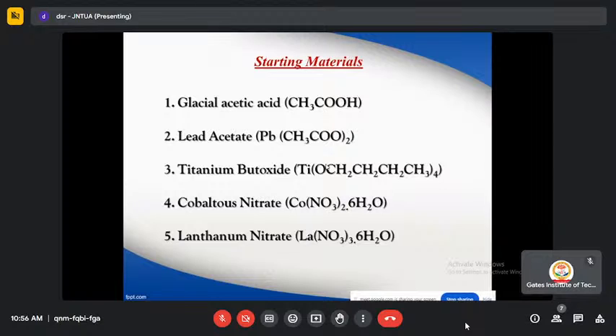So coming to the preparation, initially the materials were taken according to their stoichiometric ratio, and the precursor materials were lead acetate, cobalt nitrate, lanthanum nitrate, and titanium butoxide. All these compounds were selected corresponding to the stoichiometric ratio, and glacial acetic acid was taken as a solvent here. The glacial acetic acid solution was poured into a container and placed on the magnetic stirrer for persistently mixing the content. Later, lead acetate was added and dissolved in the solvent. After it was completely dissolved, cobaltous nitrate and lanthanum nitrate were added to the same solvent, and the temperature was maintained at 50 degrees centigrade during the whole process.